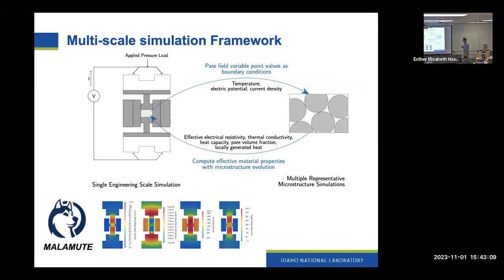Just to describe where we're going with this, we're trying to move towards a multi-scale approach like I showed for the nuclear fuel. Here we've actually set up some simulations within the Malamute repository where we do concurrent multi-scaling. So we have an engineering scale model of a chunk of material. We pass particular parameters, field variables such as the temperature, electric potential, and so on to individual phase field simulations. And then from those simulations, we can calculate things like the effective thermal conductivity and electrical resistivity, and pass that back to the engineering scale model. So we have that set up. It's really just a proof of concept at this point, but that's the direction that we're going in for electric field assisted sintering.